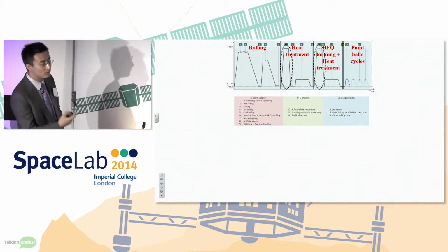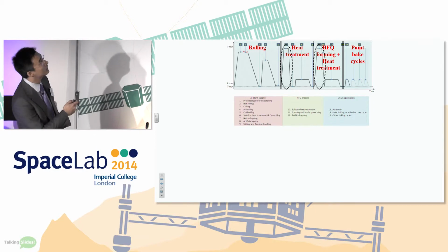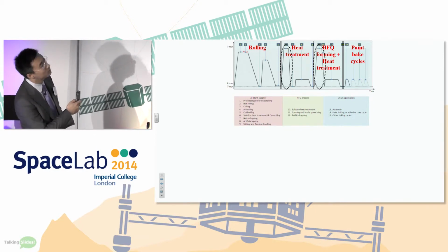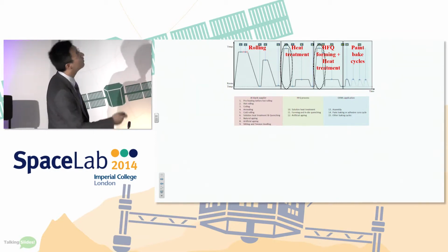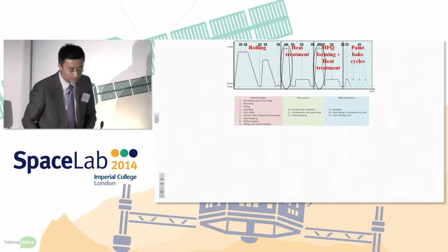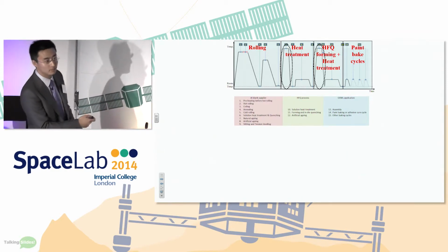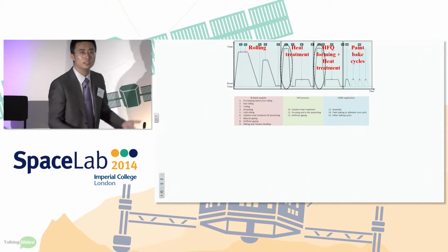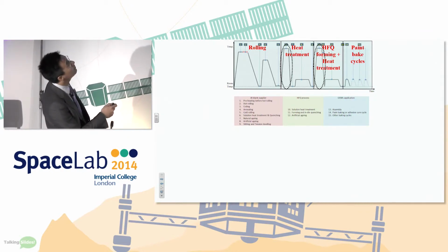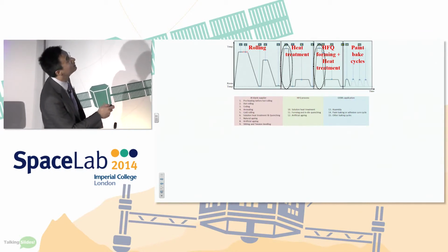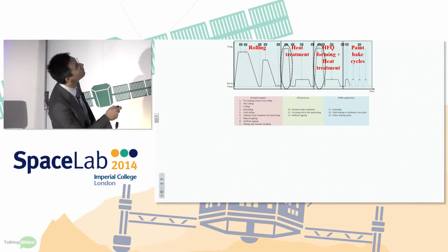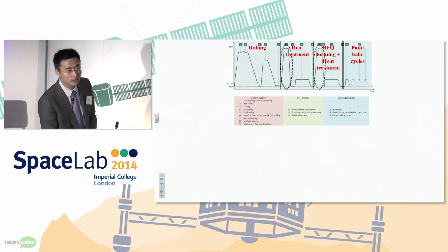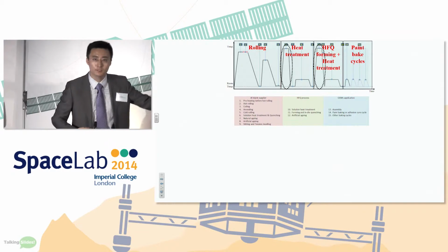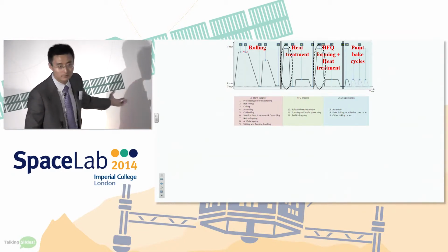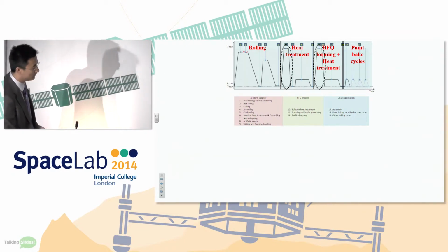If the material has a very poor ductility, a few annealing processes will take place. After that, they will solution heat treat the material, and artificial aging will take place, and then we can purchase the material in T6 or in T4 condition. And then we conduct HFQ forming, and after HFQ forming, we will conduct the artificial aging. Then the components will be supplied to OEMs, for example, the aerospace industry.